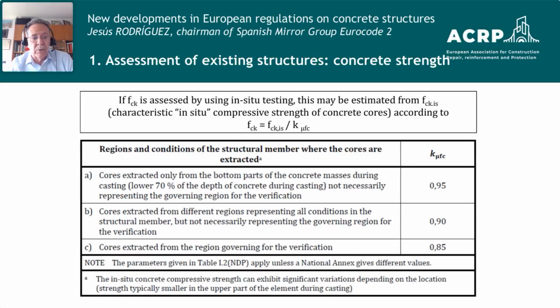This is an example on how to deal with the characteristic compressive strength of the concrete coming from drilled cores, and depending on the conditions of these drilled cores, the position, the amount, etc. Well, we have a coefficient in order to obtain, from the characteristic in situ compressive strength of the concrete cores, the characteristic compressive strength to be used in the calculations.